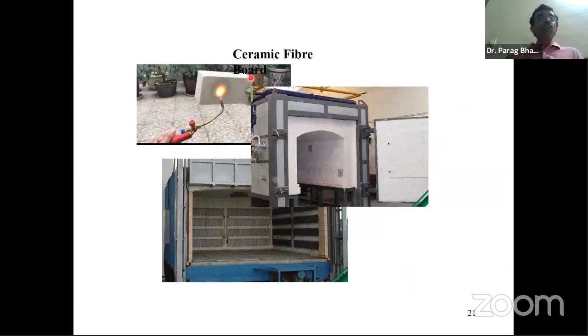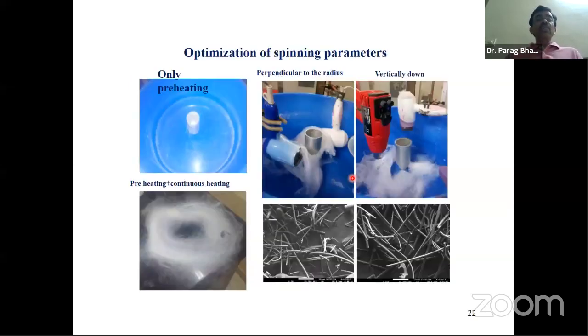You can make boards out of these fibers by compacting them, and then you can start making very lightweight furnaces. If you use this kind of material, the furnace can get heated and cooled very fast because it doesn't soak too much heat itself. The thermal mass is quite low, right? So very good opportunity. Nobody is making high temperature alumina fibers in India. This is the picture, these ceramic fibers look like this when we spin them out.